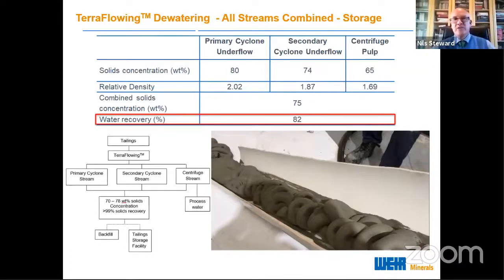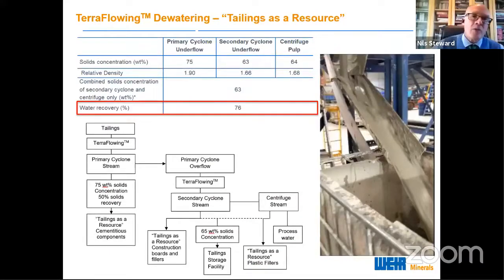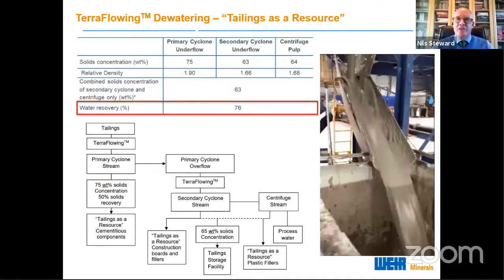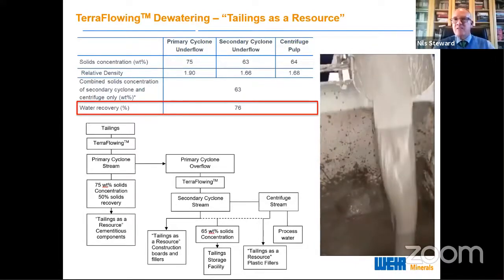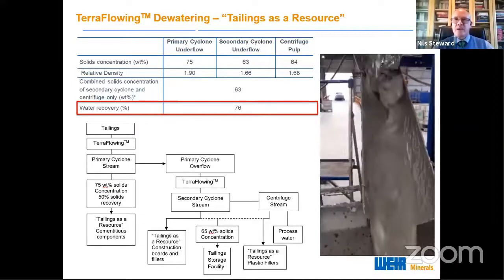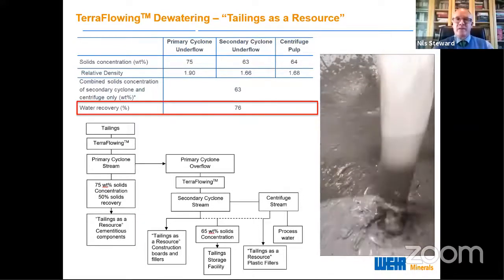If we alternatively take out the primary cyclone stream and we use that to manufacture a tailings dam embankment, which we're trialing at the moment. So we now make the assumption we've taken out the primary underflow, it's gone. We're using it to build the tailings dam embankment. What we now do is we take the secondary cyclone underflow and we combine it with the centrifuge pulp, and we get a product that has got this kind of fluidity. That is around 63 weight% solids, okay? It's pumpable with centrifugal pump.